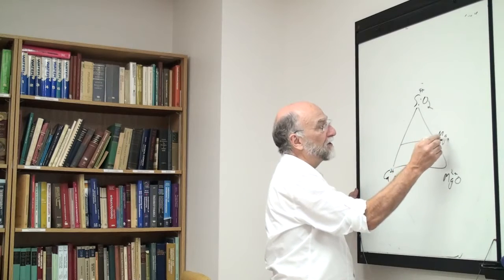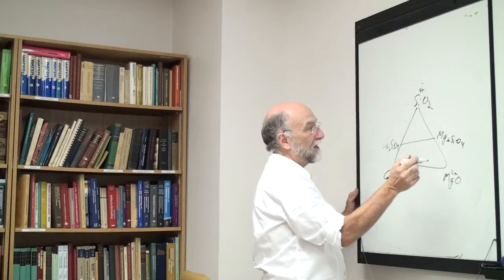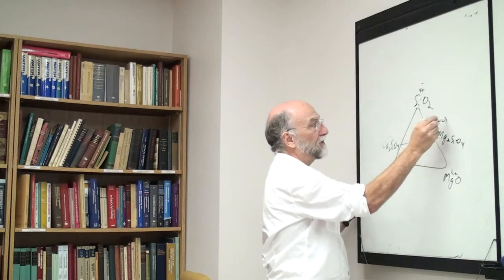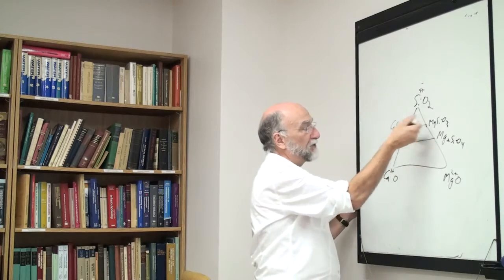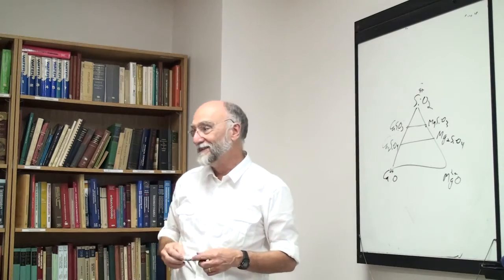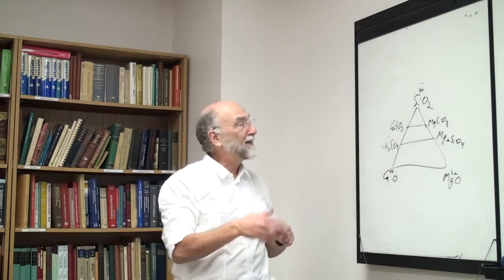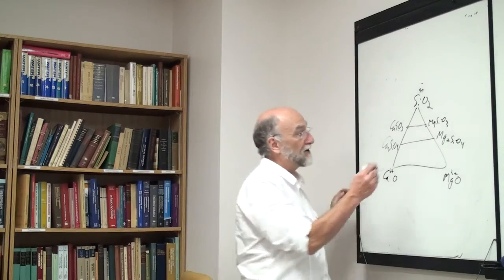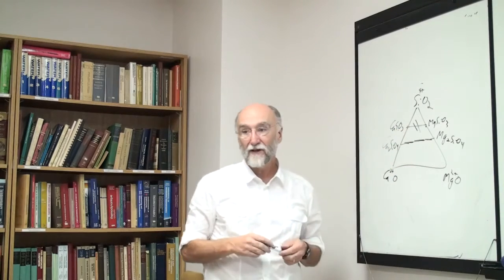So in other words, it's not quite clear, as I went from magnesium silicate to calcium silicate. Okay, and I'm going to have MgSiO3, and over here I have CaSiO3. Now, is that section quasi-binary? There you probably wouldn't know ahead of time. Sometimes I do believe that this one is, but this one isn't. So it depends, it can even depend, as you said, on the composition range or on the temperature range. So there are some regions where in this system everything is sort of like this, but in this region, not necessarily the case.